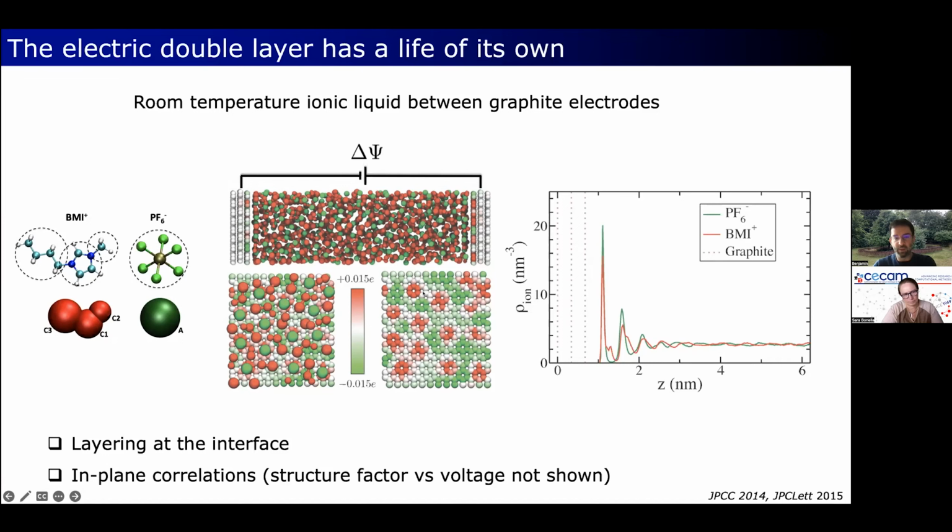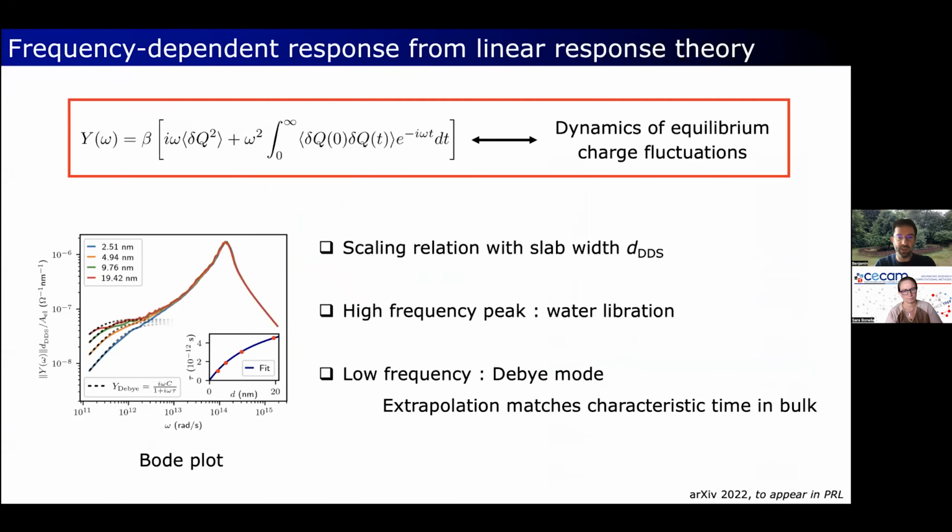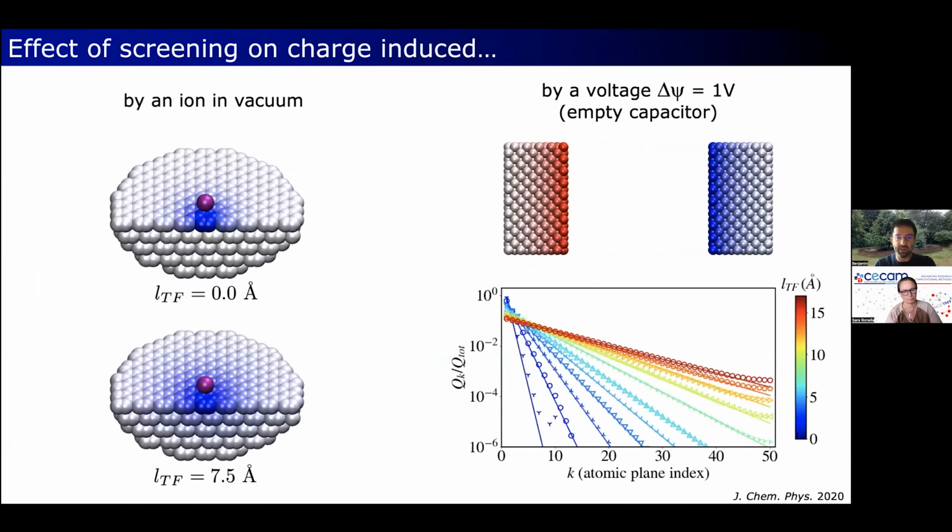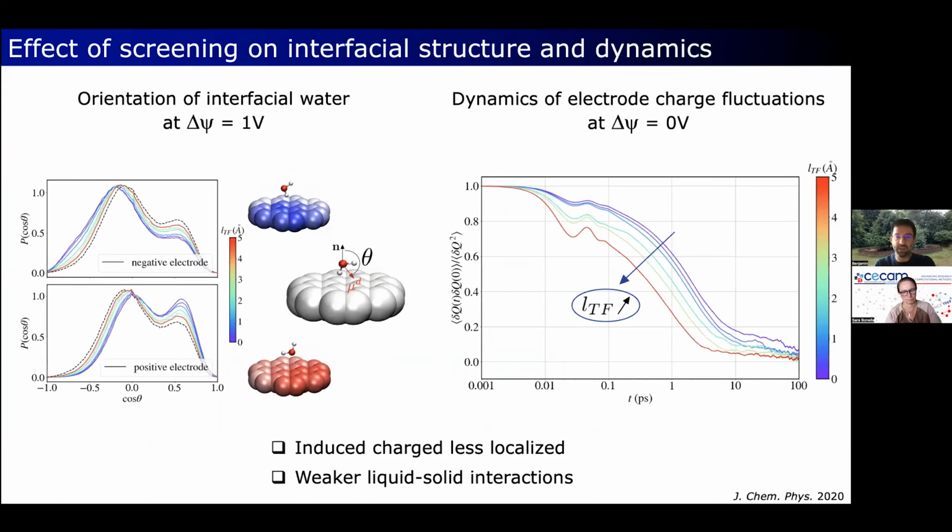And in terms of structure, at low voltage, it would probably not change much in terms of 1D structure or even in-plane structure, because it will be dominated by the ion-ion interactions. But if you look at the consequences, for example, on the interfacial free energy, and that was what I tried to illustrate for the case with a finite Thomas Fermi length, the interfacial free energy is actually quite dependent on this lateral charge distribution inside the metal.